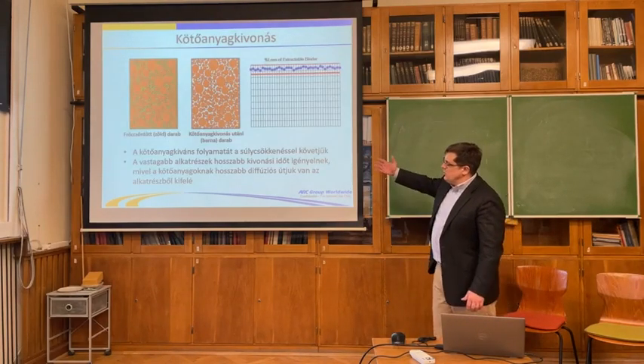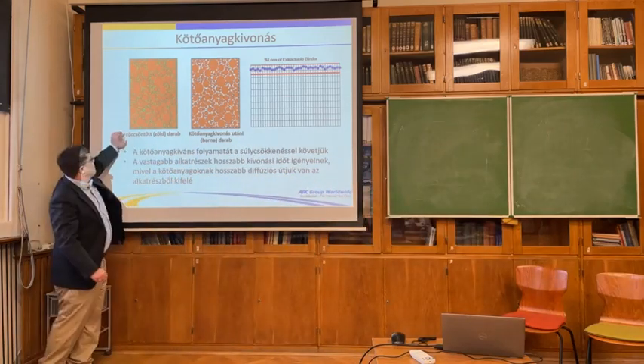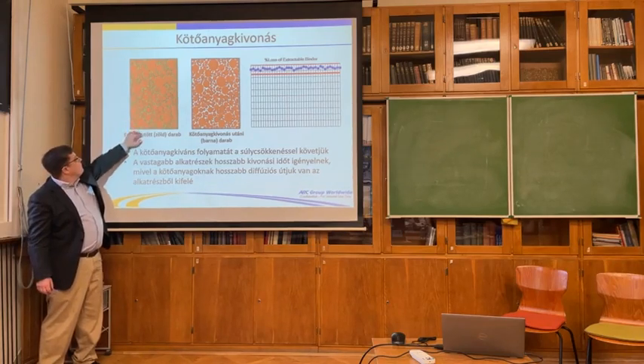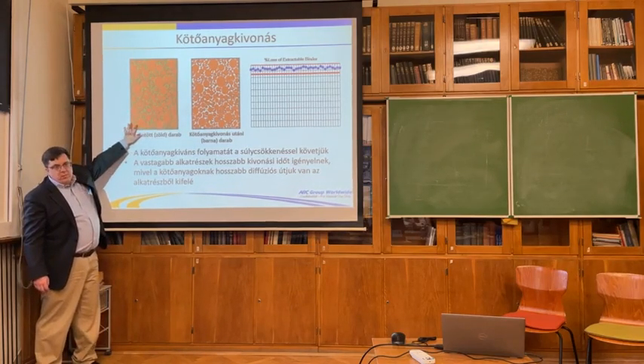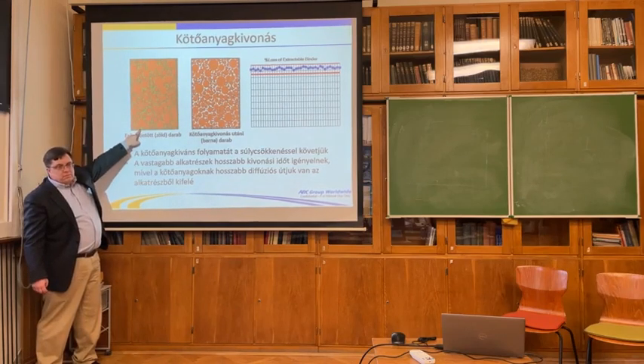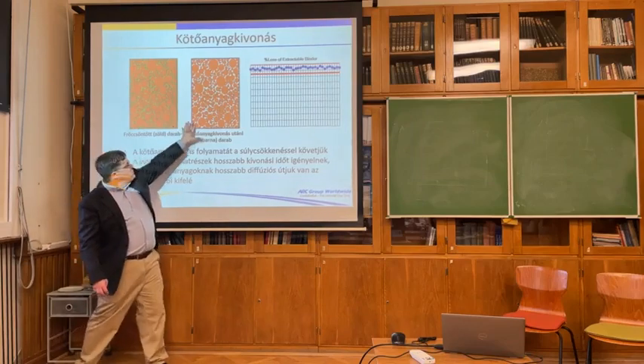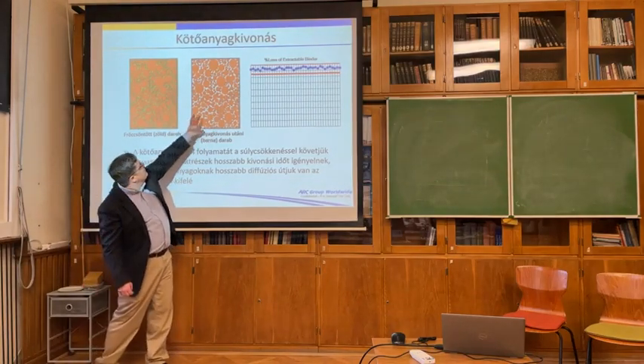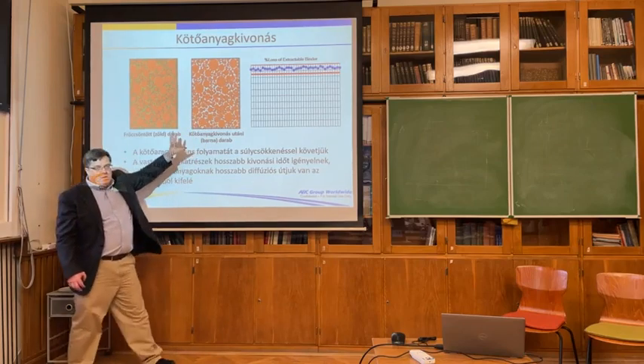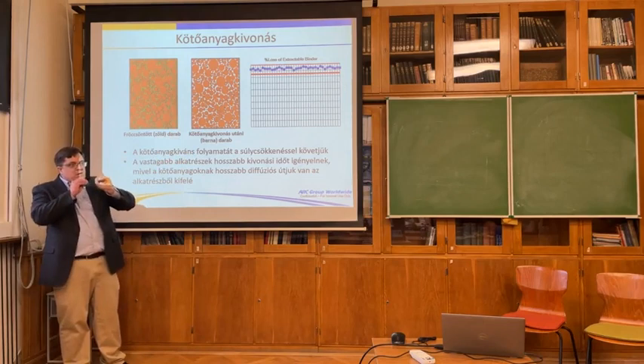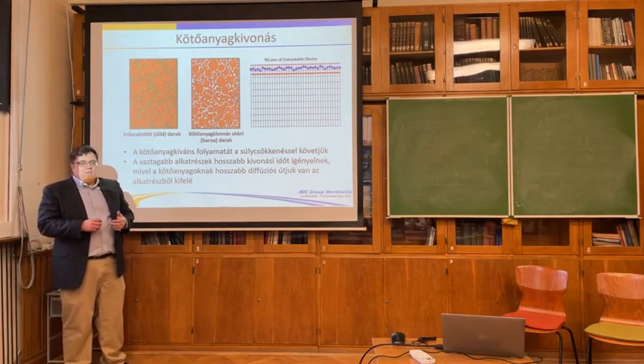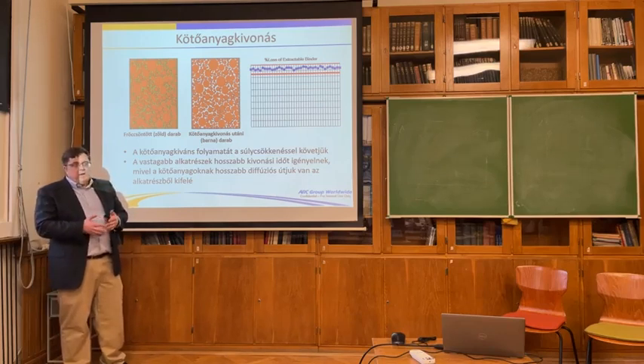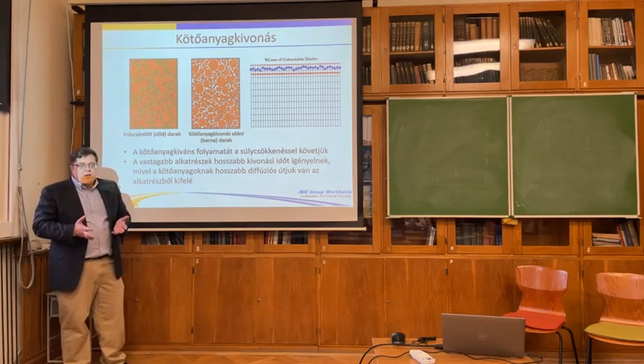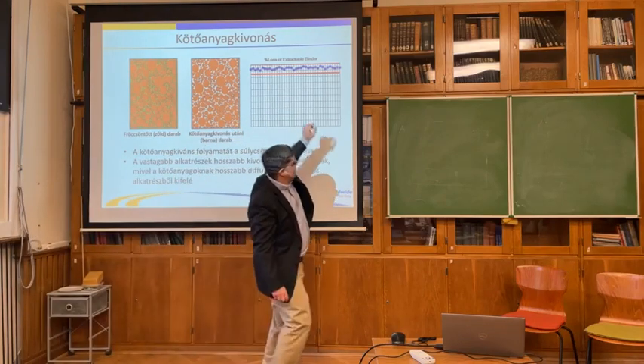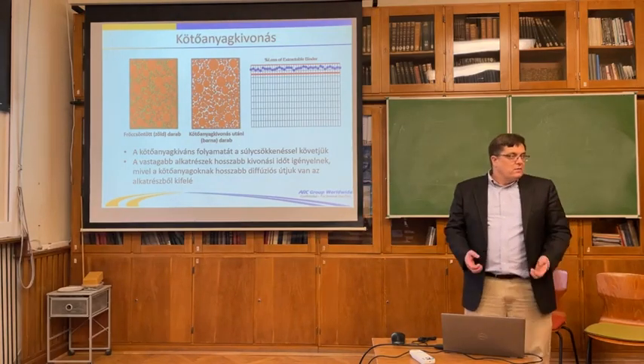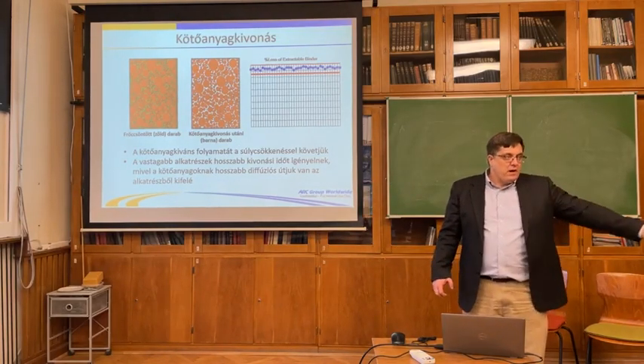So what this slide is showing here is a molded part, which we call our green part. The orange is the metal powder, and the green here is the debind line. After it goes through the debind, you've extracted most of that. You can see a little bit remaining, but it's now a very porous material. It becomes flexible or breakable. You've lost about 3 or 4% total weight, and hopefully about 90% of the total binder extraction. That's what we call the loss of extractable binder. We want more than 90% gone, so it's not going to come out in the sintering furnace. It's going to come out in the debind phase.